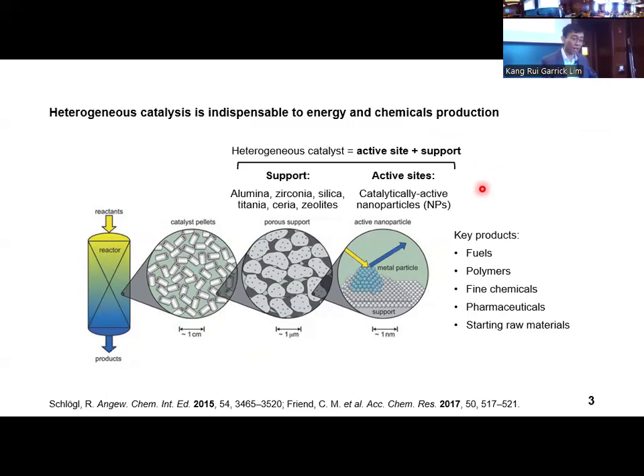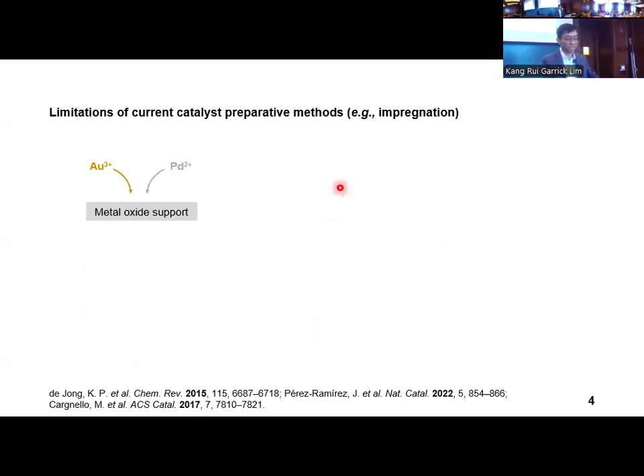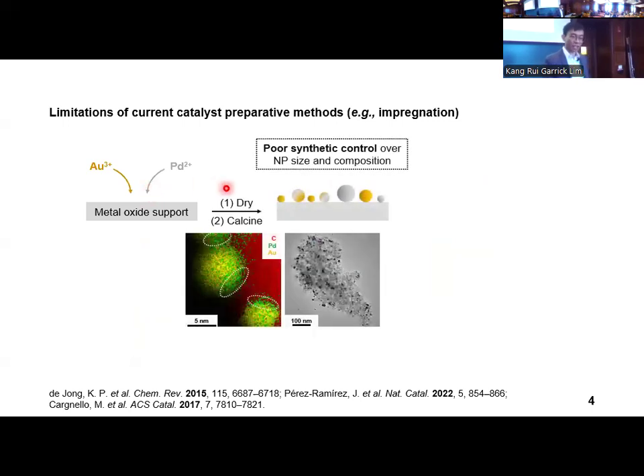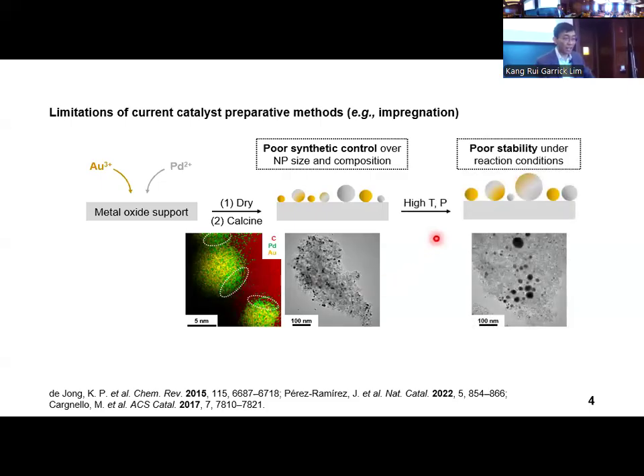These catalysts typically comprise catalytically active nanoparticles stabilized on solid supports. Industrially, such catalysts are conveniently prepared through impregnation procedures, whereby metallic precursor solutions are added to a support material. A drying and high-temperature calcination step nucleates the nanoparticles, but often leads to a broad heterogeneity in nanoparticle sizes and compositions, especially when multiple metallic precursors are used. To make matters worse, under high temperatures and pressures during catalytic evaluation, these nanoparticles often agglomerate and sinter to form larger nanoparticles, resulting in catalyst deactivation.